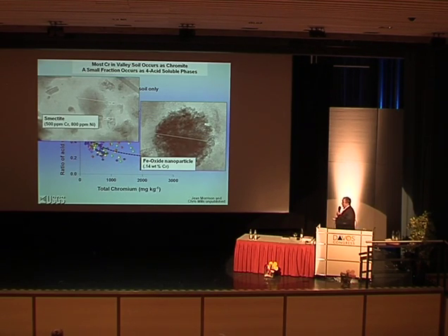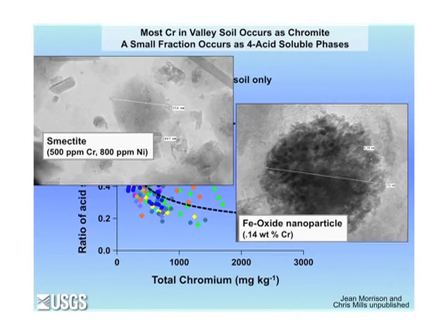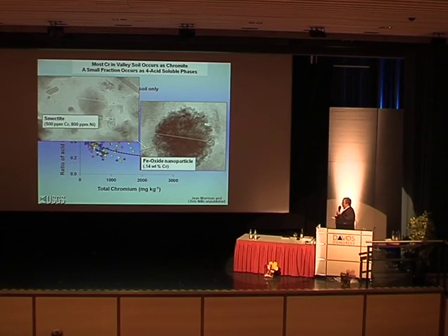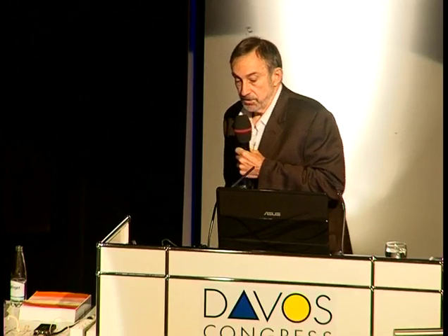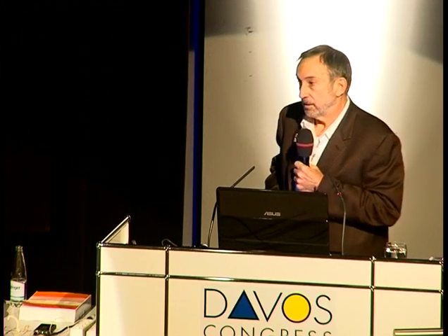These are transmission electron micrographs. This is a smectite. Its dimension is 350 nm, and it contains substantial chromium. We also found quite a number of iron oxide nanoparticles with high abundances of chromium. This is the clay fraction, or the finest fraction, and we think, just based on relative abundance of the clay fraction, it accounts for that 100 ppm. So there is some material that is non-chromite, but the bottom line is most is chromite.